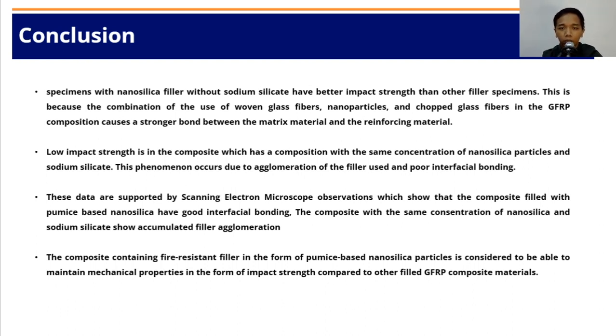These data are supported by scanning electron microscope observation, which shows that the composite filled with pumice-based nanosilica has good interfacial bonding. The composite with the same concentration of nanosilica and sodium silicate shows accumulated filler agglomeration. From the results that have been obtained, the composite containing fire-resistant filler in the form of pumice-based nanosilica particles is considered to be able to maintain mechanical properties in the form of impact strength compared to the other filled GFRP composite materials.